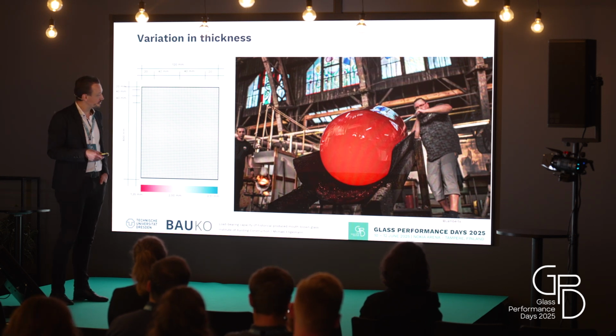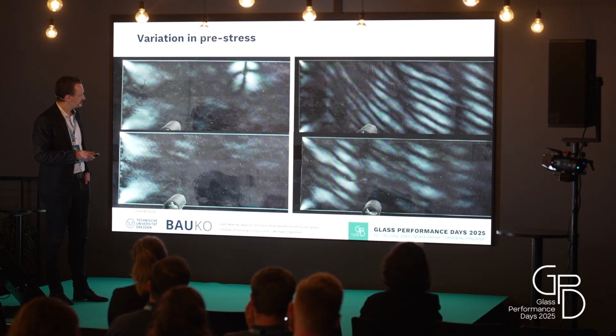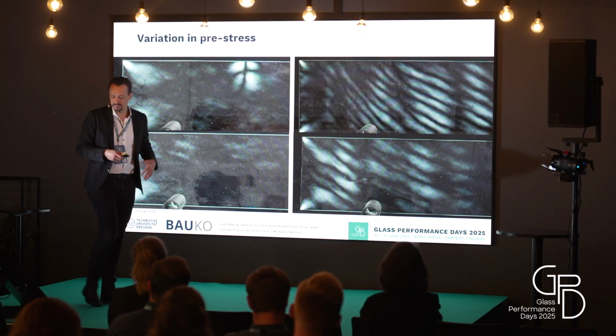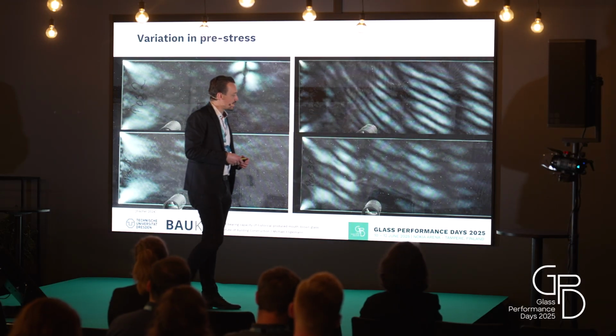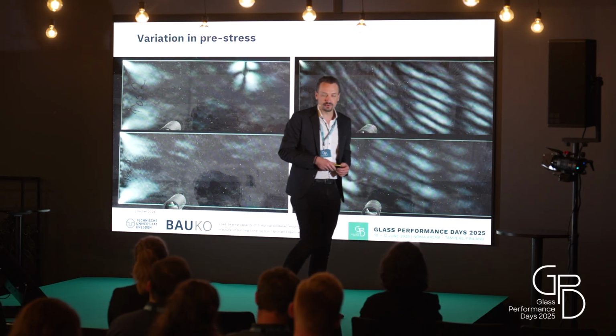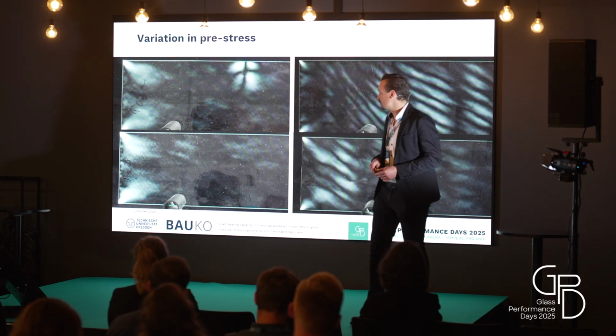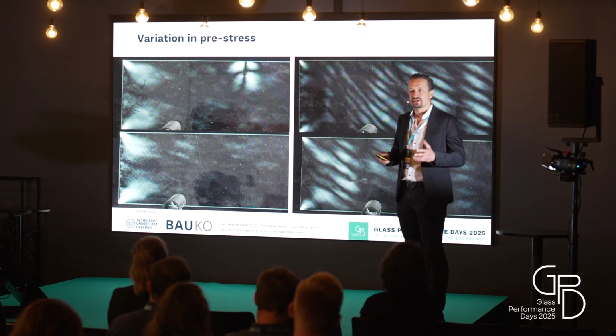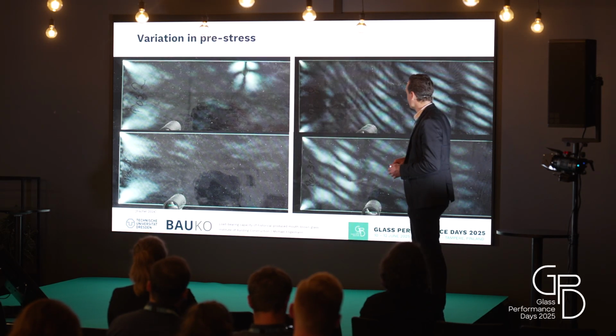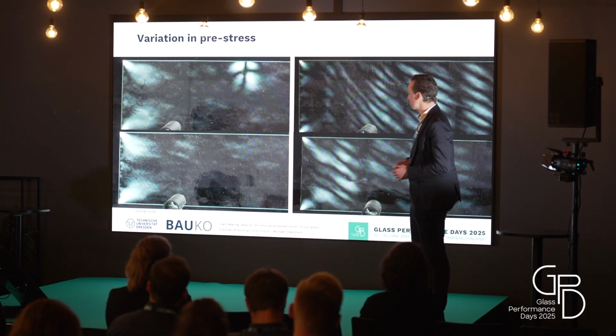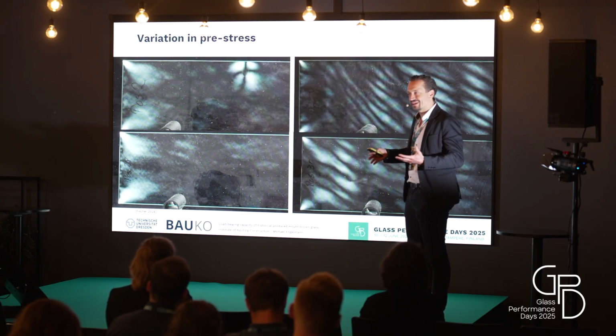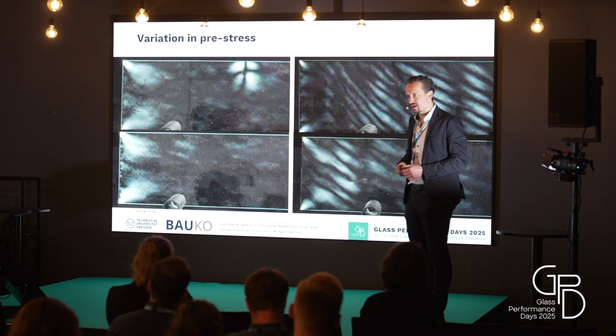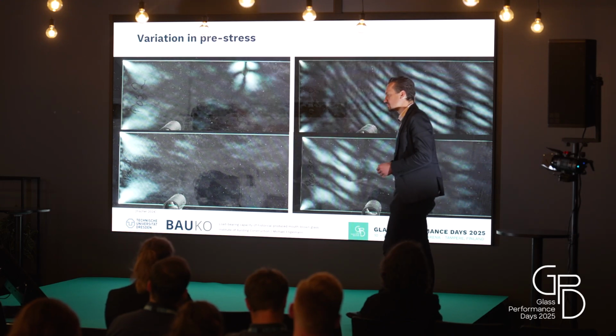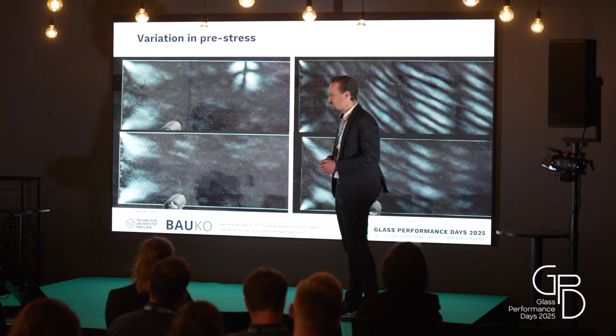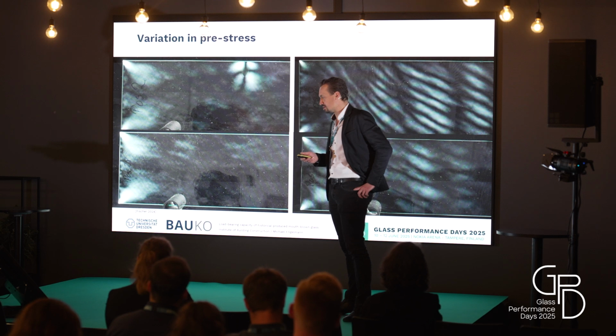Next question. After knowing the thickness, we asked, okay, can we thermally temper the glass? So half of the samples were put into a tempering furnace and were thermally treated, hoping to get something that might be fully tempered glass. And you see from those images that we can obtain a change in the glass. So we can see that we can put a pre-stress in the glass.